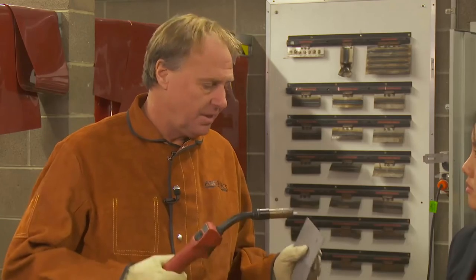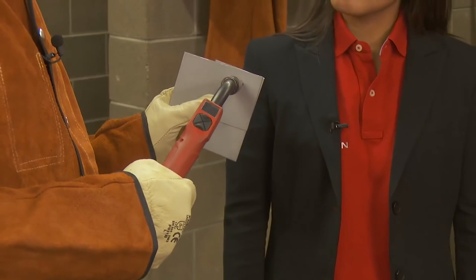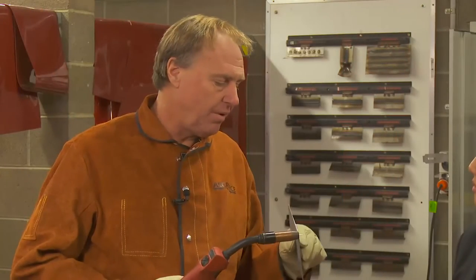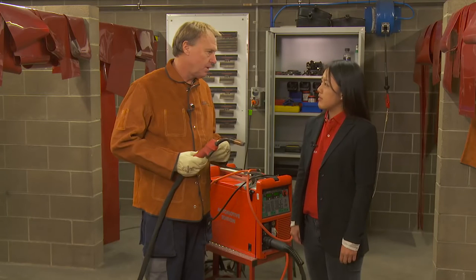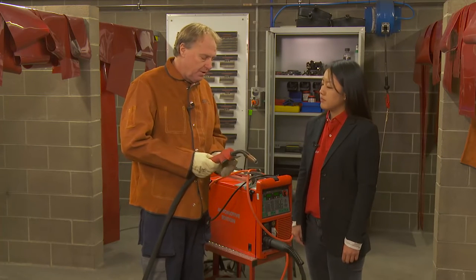Plug welding is unique within itself, as your travel angle and work angle is 90 degrees equal. The big thing with plug welding is to have a very short stick out, otherwise you're likely to bridge the top plates. So why is it so important to have the correct gun angle? The correct gun angles will affect the heat in the weld puddle and will affect the penetration that you're going to get at the end of the job.